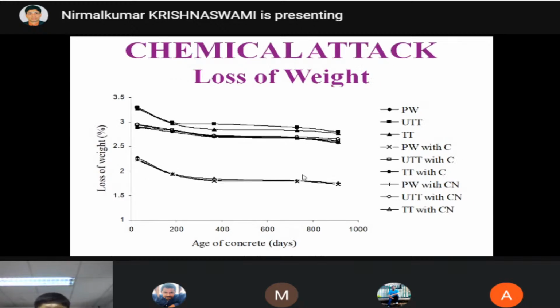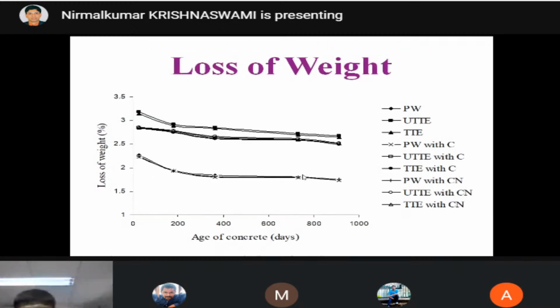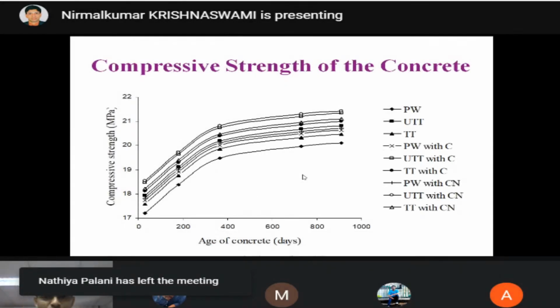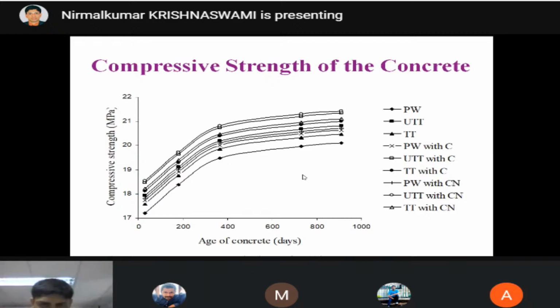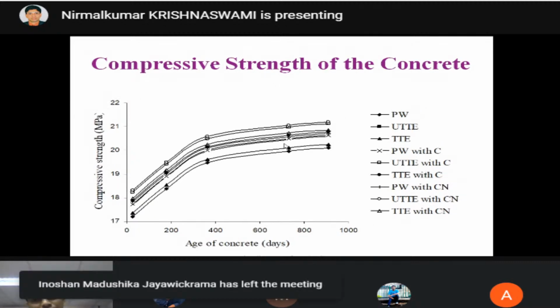This one is for tannery effluent, and this one is for textile effluent. Then coming to the compressive strength, those particular cubes we had checked for loss of weight due to acid attack, and I subjected them to the compressive strength test. You can see that initially, even for our potable water, it is around 18 or 19 MPa. When we add the admixtures, the compressive strength increases a little bit and the loss of weight decreases. This is for tannery effluent and this is for textile effluent.